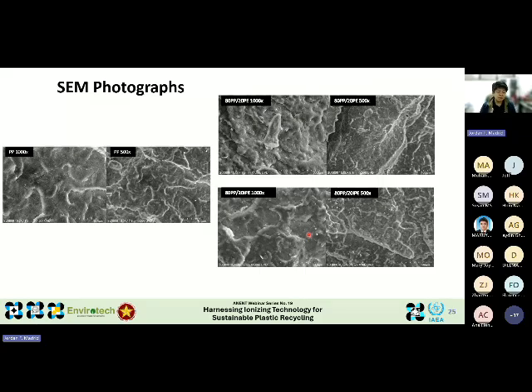Interestingly, when we looked at the samples prepared using irradiated HDPE, we observed a slight decrease in the number of hollowed and protruded regions, suggesting perhaps that irradiation improved the compatibility between the two components, leading to a relatively more uniform blend.